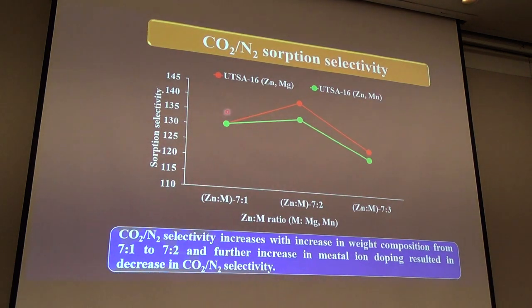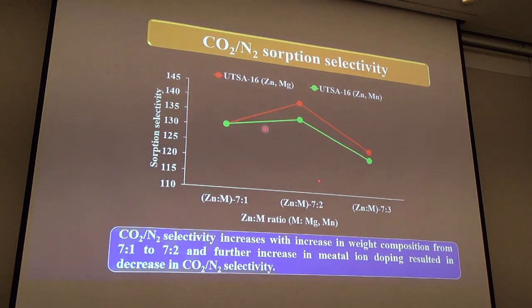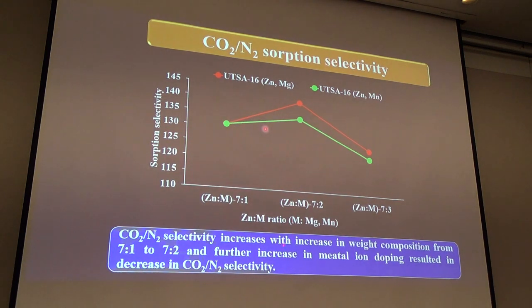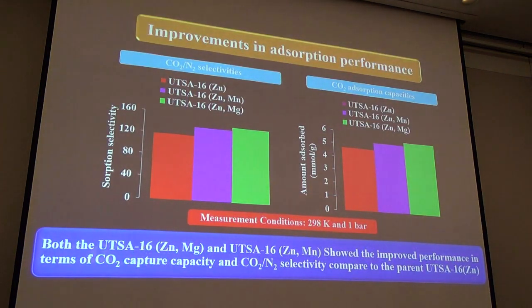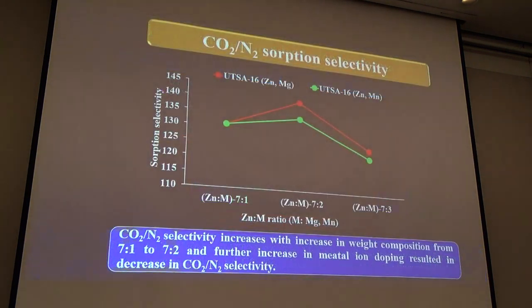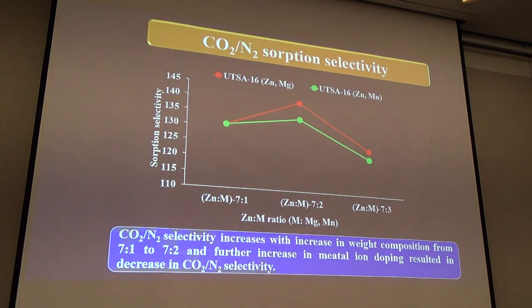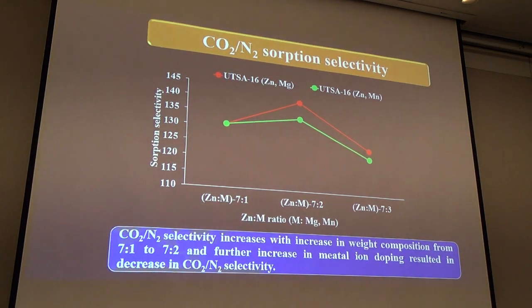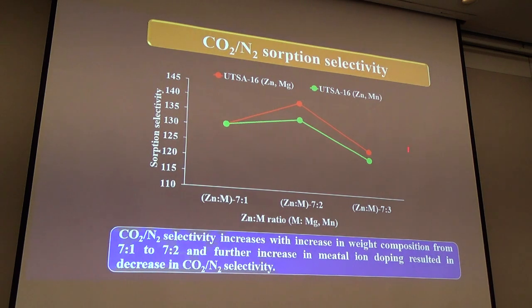For practical application, selectivity is also important in adsorption performance. CO2 over N2 selectivity was measured by the ratio of CO2 adsorption capacity at 0.15 bar divided by N2 adsorption capacity at 0.85 bar. As with CO2 adsorption capacities and N2 adsorption capacities, the selectivity of the bimetallic MOFs also increases with the increase in metal ion doping. However, excessive addition of metal ion doping leads to a decrease in CO2 over N2 selectivity.